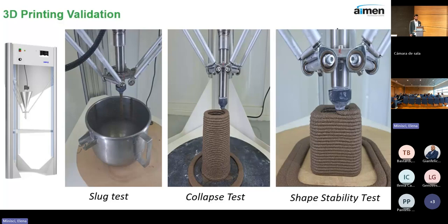The second test is the collapse test. As you can guess, you have to print until collapse. In our case, it's a cylinder, and you have to measure how many layers are printed before collapse, and it's also important to check the mode of failure. It will be elastic or buckling, and depending on that, you can change your formulation. The last one is the shape stability test. You have to print a standard part, and you have to check the stability of the extrusion, the dimensions of the layers, the width, the part, and so on.